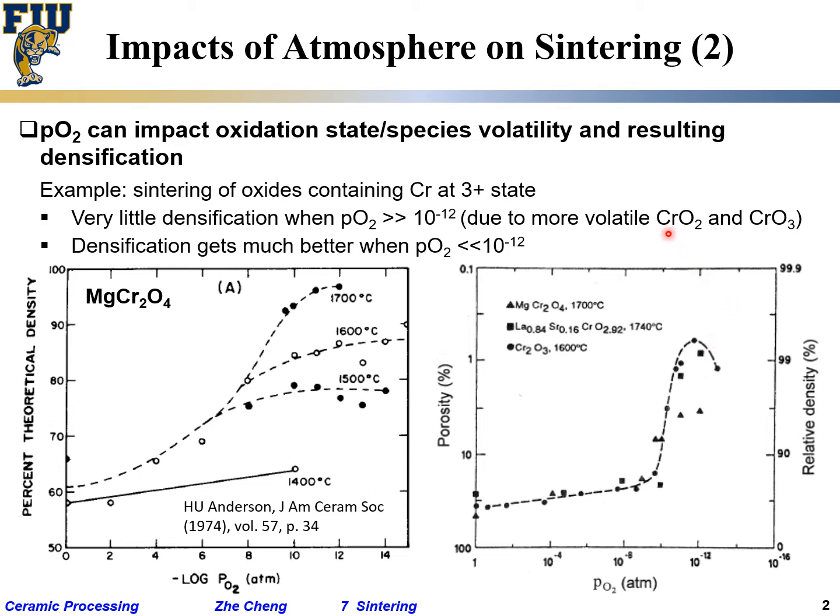And what you learned is, no matter what material is between these 3, you want to sinter in an atmosphere that has low PO2. Low PO2, 10 to the minus 12, something like that. But not in oxygen, or in air, which is roughly here. Make sense? Pure oxygen is here. Air is slightly lower than pure oxygen. But here we end up with density around 80, 85, but not full density.